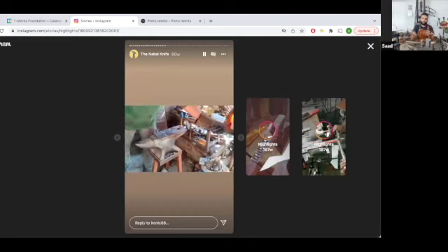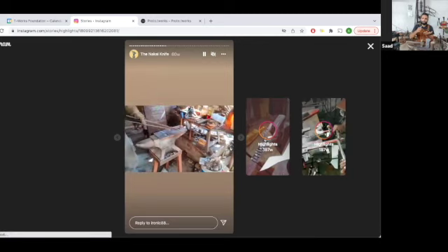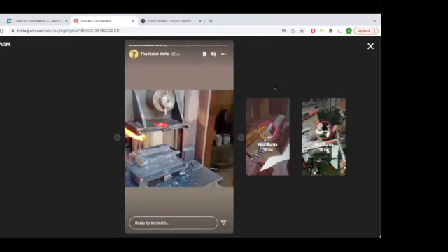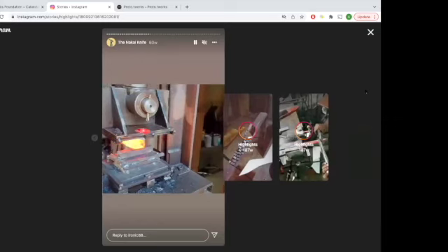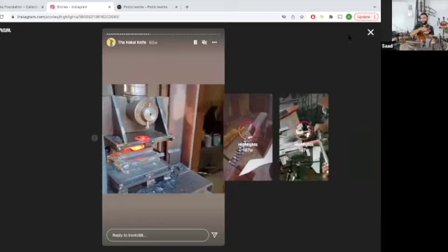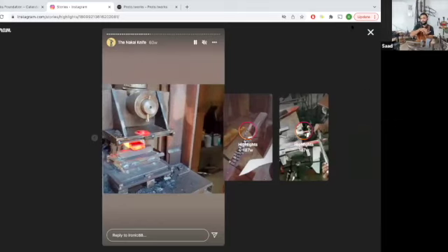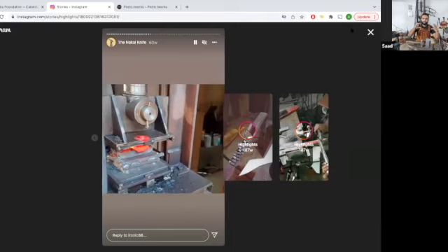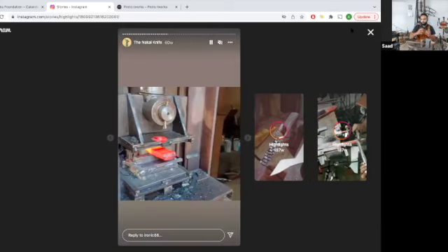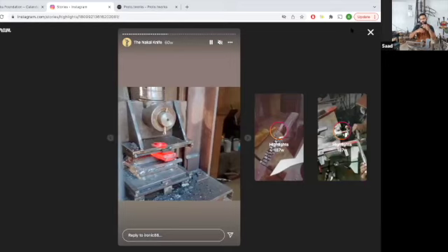So coming to your question, ideally you start with about 20 layers, and you can finish forge welding those 20 layers. So now I know I have a solid 20 layer billet, and then I fold it once more. So that now I have only one forge weld, and I get 40 layers. And then I fold it once more. I've got another one forge weld, and I've got 80 layers. Fold it again, keep folding it until you can build up your layer count.